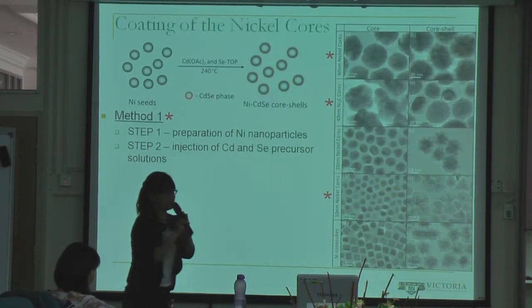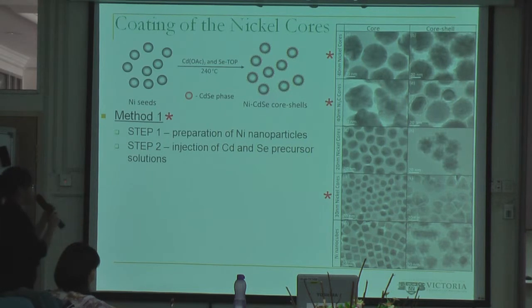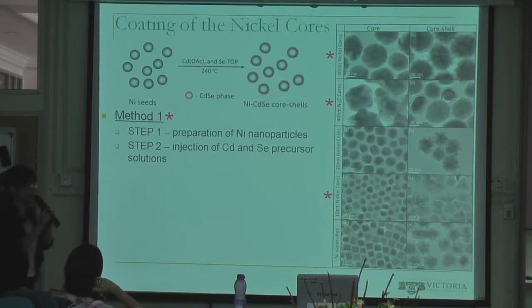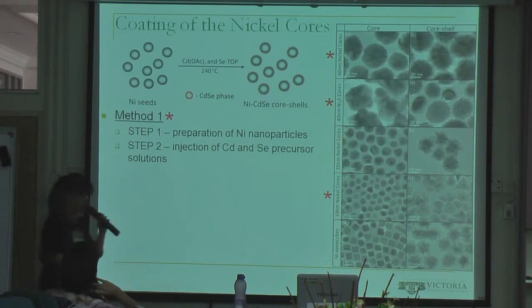As I have mentioned before, the preparation of these bifunctional structures is essentially a two-step process. First one is the preparation of nickel nanoparticles, and then the second step involves the injection of the cadmium and selenium precursor solutions. Actual experiments carried out in the lab show that this two-step process is only applicable for 3 cases, which are the 40 nanometer nickel cores, 40 nanometer nickel carbide, and the 10 nanometer nickel cores. What happened to the other 2 cases, the 20 nanometer one and the nickel nanocubes, is this.